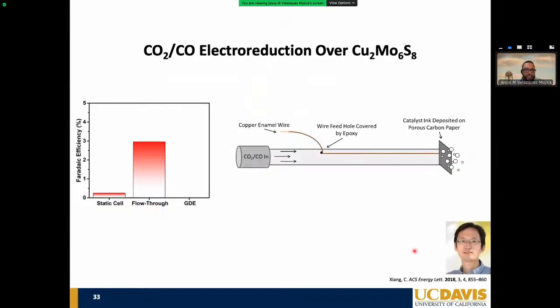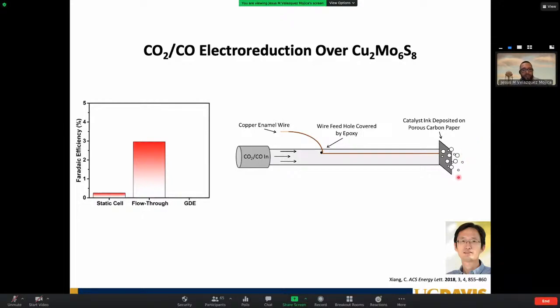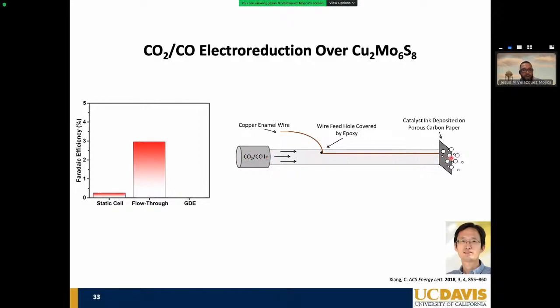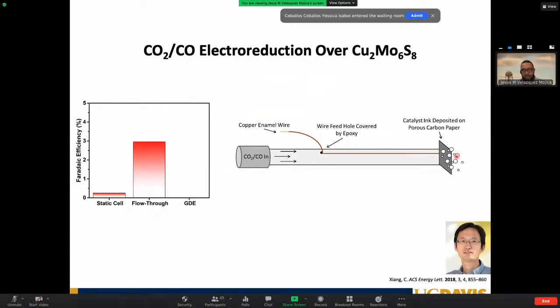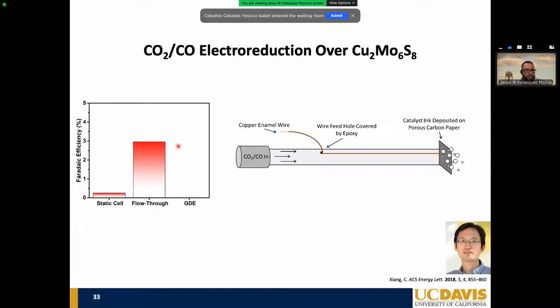We are taking inspiration from our colleagues over at the Joint Center for Artificial Photosynthesis to do these really simple flow-through electrodes. What this allows us to do is, instead of being inhibited by the solubility of CO2 and trying to saturate the electrolyte, then doing the electrochemistry, CO2 is actually being delivered through this quarter-inch glass tube and goes right through this porous carbon. So the input of CO2 is much more ready and not hindered by solubility issues. Some preliminary results are already showing us that if we could fine-tune catalyst loading, CO2 delivery, and also the electrochemical environment or the potential applied to our catalysts loaded in this porous carbon, we should be able to continue to see improvements.